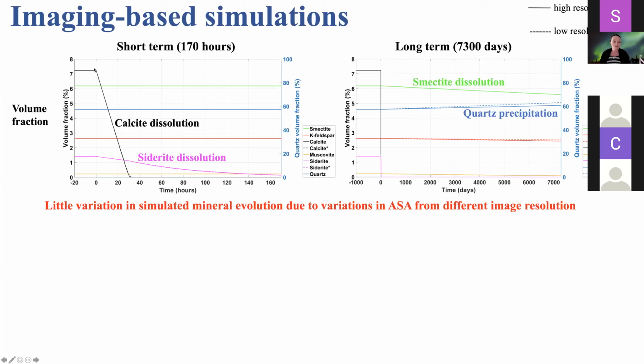So we see with the introduction of CO2 saturated brine, you have rapid dissolution of calcite. You also have dissolution of siderite, but you'll also notice that the variation in the simulation results using the surface areas from the high and low resolution images is really minor. If we look at longer time scales, we start to see dissolution of smectite and precipitation of quartz. And there is some slight variation in the simulated extent of quartz precipitation depending on the surface area value that you used. But overall, the variations in volume fraction due to different surface areas is pretty small.